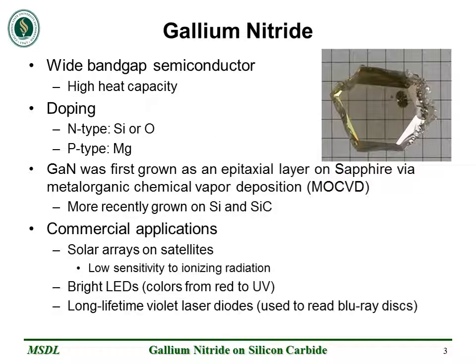Gallium nitride is a wide bandgap semiconductor with high heat capacity. It can be doped to N-type using silicon or oxygen, and it can be doped to P-type using magnesium. Gallium nitride was first grown as an epitaxial layer on sapphire via metal organic chemical vapor deposition, or MOCVD. It is more recently grown on silicon or silicon carbide despite the slight lattice mismatch.